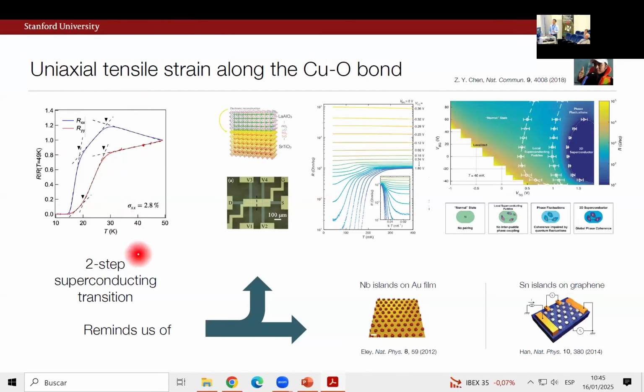In the interest of time, at least for our eyeballs, this is quite characteristic of a well-developed set of ideas and phenomenology. Maybe I'll just talk you through this picture. Mesoscopic or artificial systems where you take a superconducting array of puddles and an underlying metal, in this case gold, and I think in this case it was gated graphene. So the idea is in this kind of situation, you often see a two-step transition because first the puddle, or the niobium island here, goes superconducting, and the second transition is when there's global phase coherence via the proximity effect in the gold film. And so both in artificial systems and in naturally occurring systems, like LAO/STO, you can see this kind of game. Again, the onset of first local superconducting puddles and then global phase coherence is the thing that we think we're seeing here.